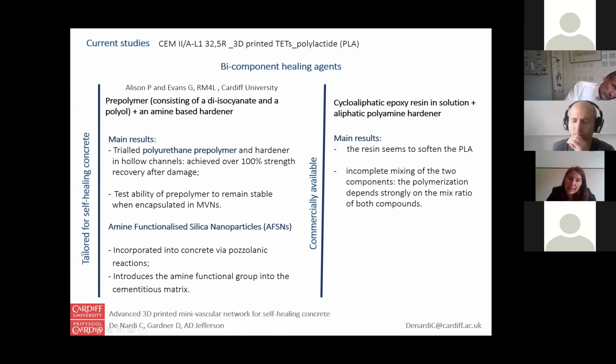And then we moved on to a tailored self-healing bicomponent glue, where we use a polyurethane pre-polymer and an amine-based hardener. We are working together with Alison P and Evans G here at Cardiff University. First of all, we trialed the pre-polymer polyurethane and the hardener in 2 different hollow channels, and they worked really very well, achieving over 100% in terms of strength. But when the pre-polymer, the polyurethane, is stored inside the minivascular network, it is not stable. So we need to work a little bit on the stability of the pre-polymer.